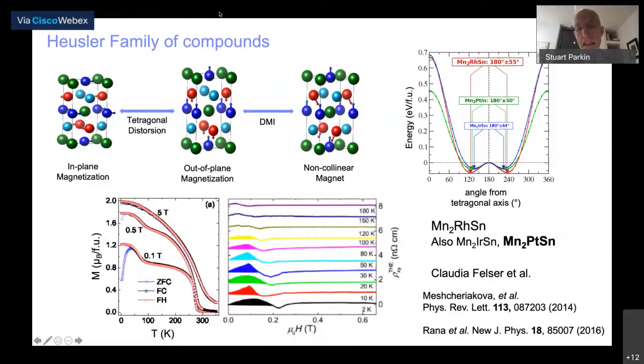And along the tetragonal axis, the structure consists of planes formed from manganese and platinum, alternating with planes formed from manganese and tin. And in each of these planes, the magnetic moments are oriented parallel, but from one plane, manganese platinum, to the next one, manganese tin, the moments are oriented anti-parallel to one another. And it turns out the moments in the two planes are slightly different, so there's a net magnetization moment. And what was discovered a few years ago, actually, we showed that these types of systems develop something called a topological effect, which means that there's an interesting new scattering mechanism, which is most likely derived from non-collinear orientation of the magnetization.